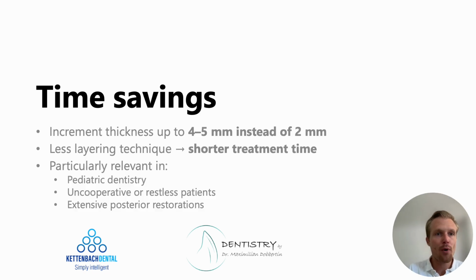An important point about the usage of bulk fills, as I said before, is time savings. When we use an increment thickness of up to 4 or maybe 5 millimeters instead of 2 millimeters, we can work more efficiently, more effectively. We need a shorter treatment time because of using fewer layers, but on the other hand, reducing time also sometimes reduces possible errors, because time is always working against us in terms of isolation protocol.